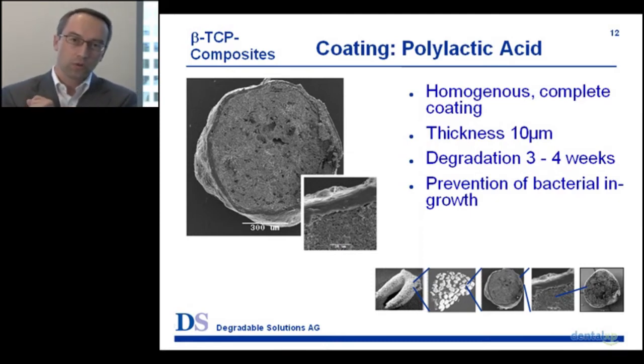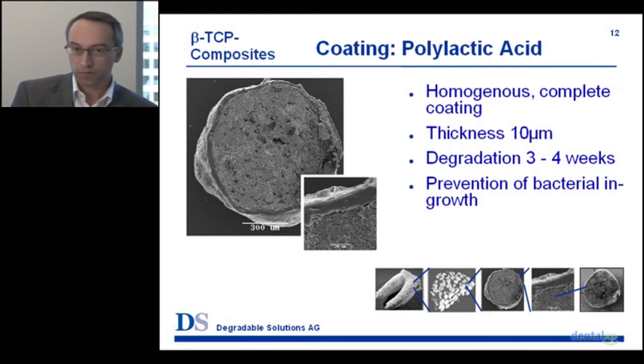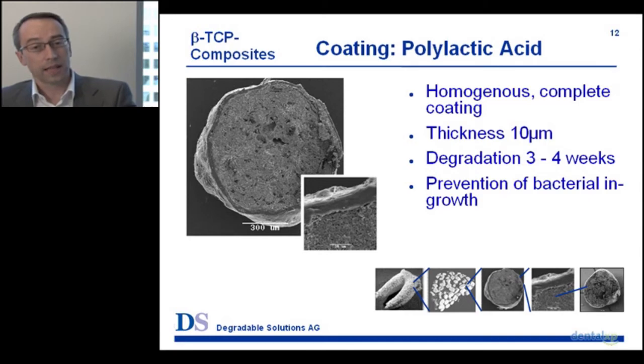So next, and this is the innovative step that we did, we coated each granule with 10 microns of a polylactic acid. So a very, very thin coating that would allow us to stick the granules together. This coating is there for 3 to 4 weeks, and after that it is resorbed completely by the body. This coating has another very interesting benefit. It kind of prevents bacteria from growing into this porous granule.